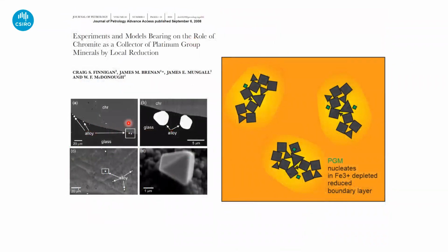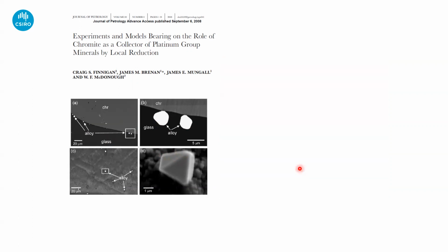So this is a fairly well-established model for formation of the iridium inclusions in chromites, and that is from the classic paper from Finnigan et al. 2008, where they showed that if you've got a chromite crystal growing, it generates a redox boundary layer. Within that redox boundary layer, you can nucleate iridium grains, and they get trapped in the chromites. Basically, PGM are nucleating in an Fe3+ reduced boundary layer, and the reason for that is because of the really strong fO2 dependence of PGE solubilities.